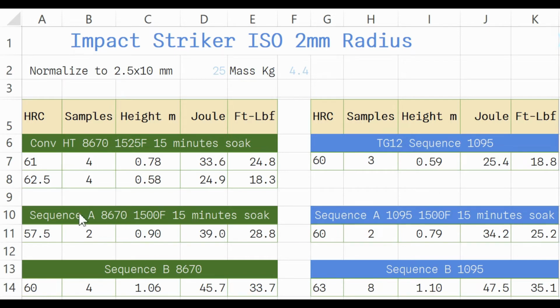And then I did another experiment, and I call it A here, where the soak is at 1500 degrees for 15 minutes, and 8670 only comes out at 57.5 Rockwell, and the foot-pounds at break are just 28.8. For the 1095, the result now is 25.2, but this is 57 or 57.5, and this is 60.